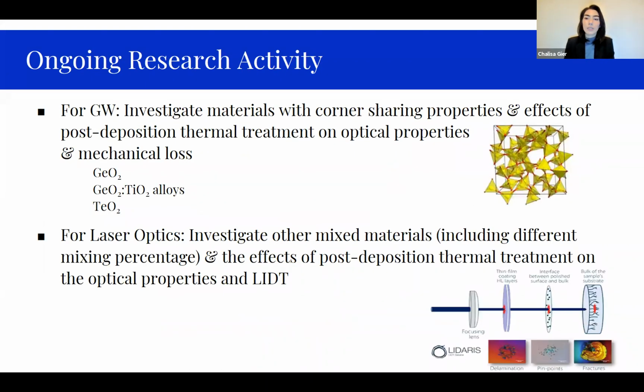For our ongoing research activity for gravitational waves, we are investigating materials with corner-sharing properties, including germanium oxide and also germanium titanium alloys, where the titanium will be used to increase the germanium refractive index. This is based on the findings published by Paisley in 2019 while studying the zirconia doped tantala films. He showed that the mechanical loss is correlated to the fraction of corner sharing in the amorphous structure, and also that annealing increases the corner share polyhedra and decreases the edge and face sharing polyhedra.